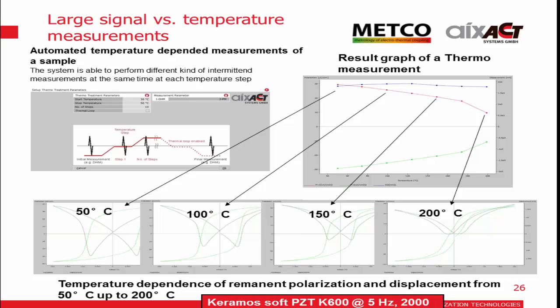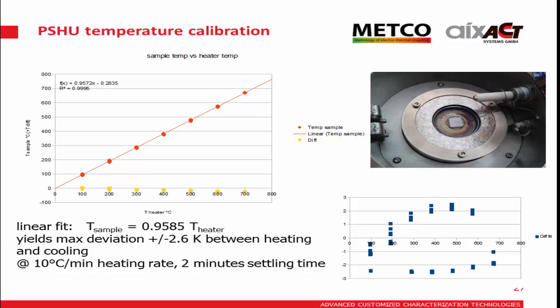And this was now also extended for the high temperature values. So this is for the piezoelectric sample holder. We did also temperature calibration using a similar setup, and we could also see that there is a similar change in temperature as in the DBLI system, and also the method gave us some ideas to improve that, from around ±5 Kelvin to ±2.6 Kelvin now. If you raise the temperature and go back to 0, and the heating rate here was about 10 degrees C per minute, so that you can run a sample sweep within 1 day.